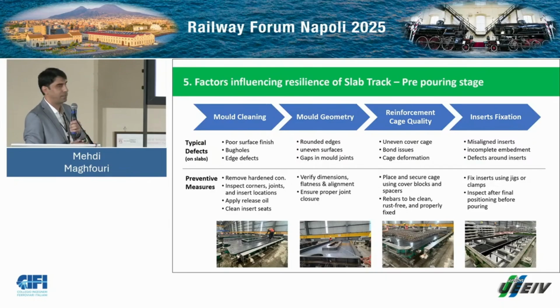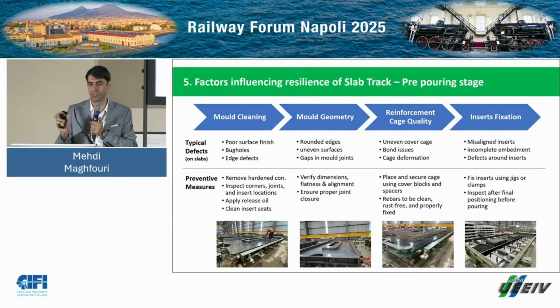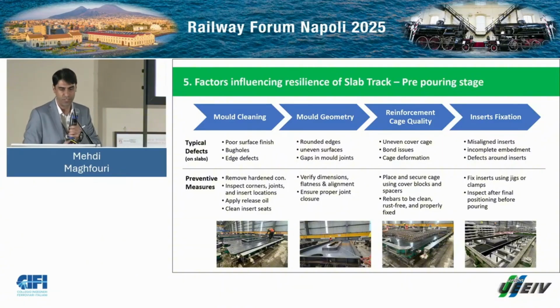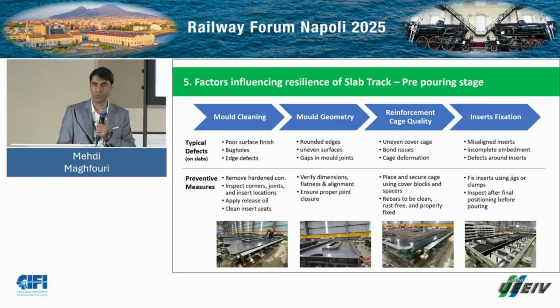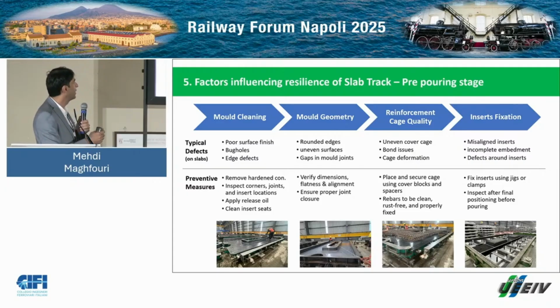Mold cleaning, as I just mentioned, is one of the steps. If there is no proper mold cleaning in place, poor surface finish, bugholes and edge defects might happen. What we can do is remove the hardened concrete, inspect the corners, joints, and insert locations, apply release oil, and clean the insert seats.